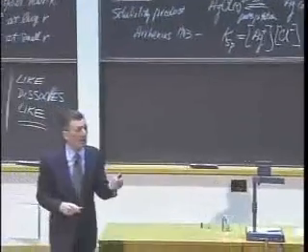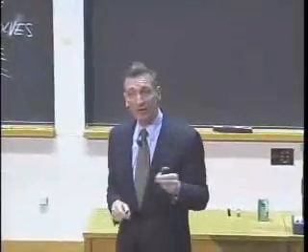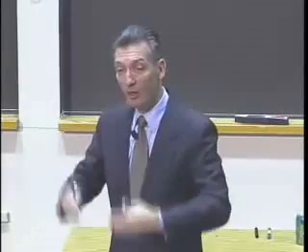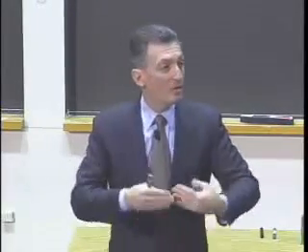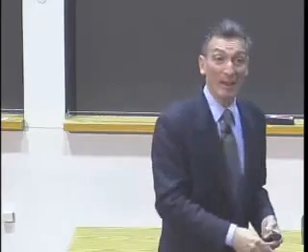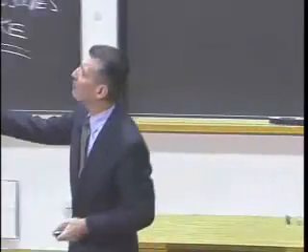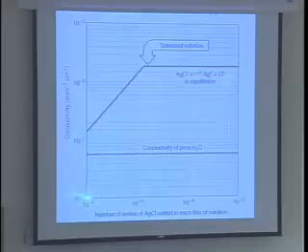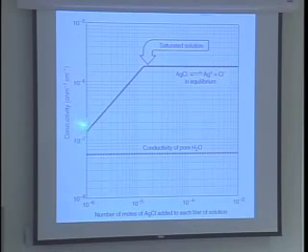So by measuring conductivity as a function of concentration, we can determine if we are dissolving the silver chloride, as opposed to we keep adding it and it just sinks to the bottom. So let's look here. What we find is as we add silver chloride, the conductivity of the solution rises up to a maximum value at around 10 to the minus 5 moles of silver chloride per liter of solution.